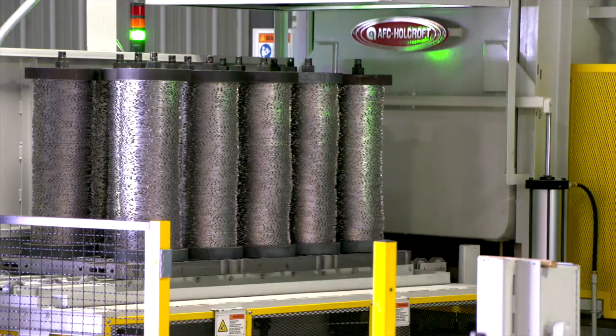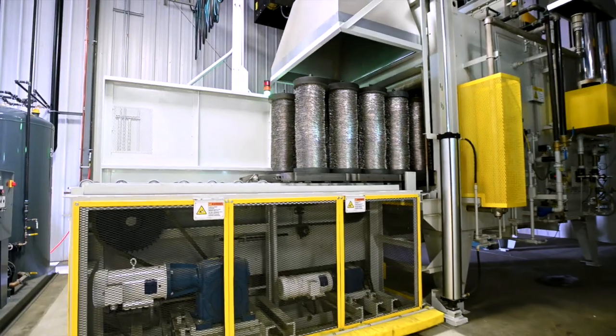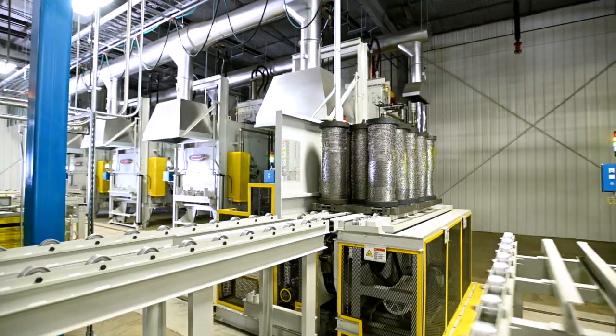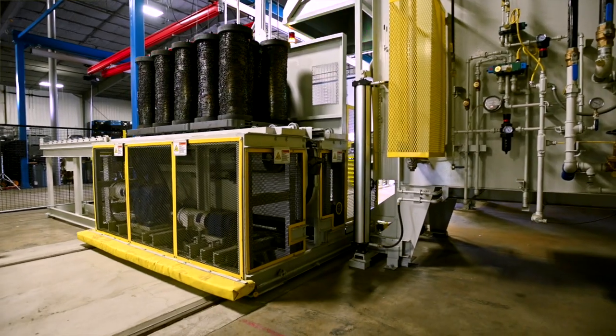The heat treating process we're using here at Feintool is a stress relieving process with an oxygen deprived environment. We control the temperature in the ramp up phase as well as our soak before we hit the transition temperature, and then we bring that temperature back down at a controlled rate below the oxidation level before reintroducing those parts into the original atmosphere.